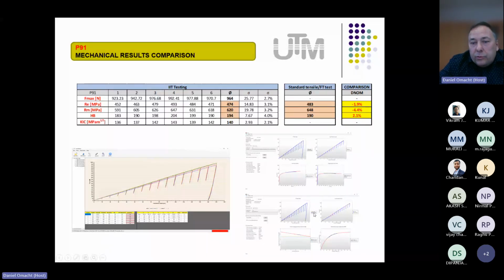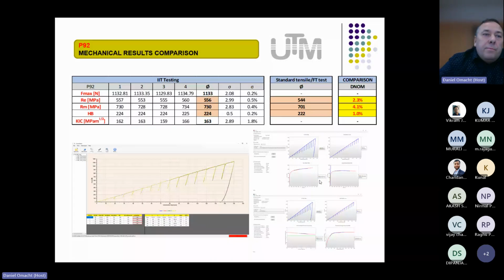Here you can see some details from the evaluation software. The same as you saw for P91, we did on many materials, P92, P22, plus materials which are used in nuclear research, nuclear power energy, and so on. P92, for example, here you can see 4 tests, and the proof of the accuracy of the machine which we created is visible in these curves. The standard deviation is 0.2%. So the curves are almost the same. Again, if you look at the comparison, you can see the result: 2% difference for yield strength, ultimate tensile strength is 4%, and Brinell hardness is 1%.